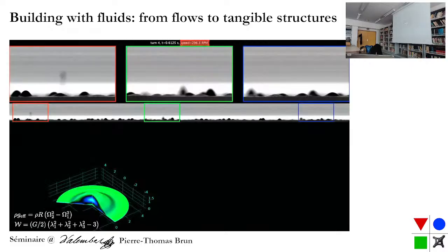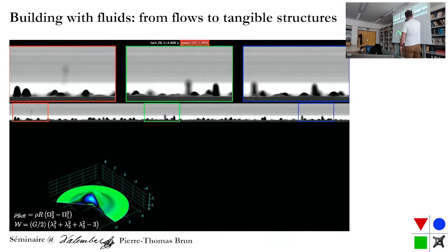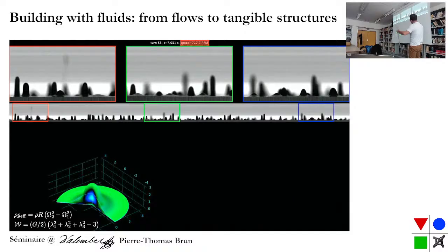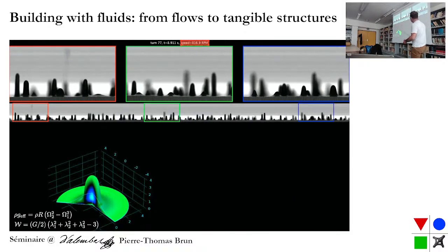Could you, on the first experiment you showed, the drops were aligned on the left and not aligned on the right. Yes. So that's the boundaries, right? Because the printer has to come and start to drag. So that's more like boundaries effect. Okay, so if we had, no, we have dislocation and defects, but in this case, that was not the case. Oh, it works perfect. Okay, so here goes the movie quickly, and so yeah, you see the acceleration and these droplets. They actually stretch and create these hair-like structures.